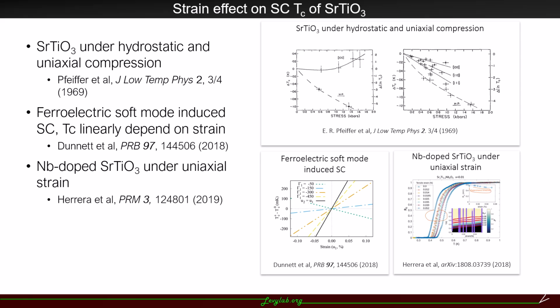This is supported by a recent experiment where they saw a nearly 50% increase in critical temperature in niobium-doped strontium titanate under tensile strain of 0.05%. We think it is appealing to see what would happen if we strain the lanthanum aluminate strontium titanate heterostructures.